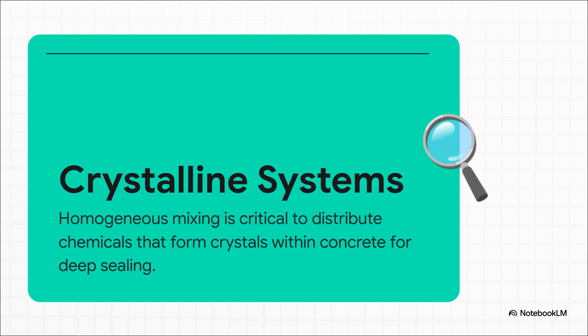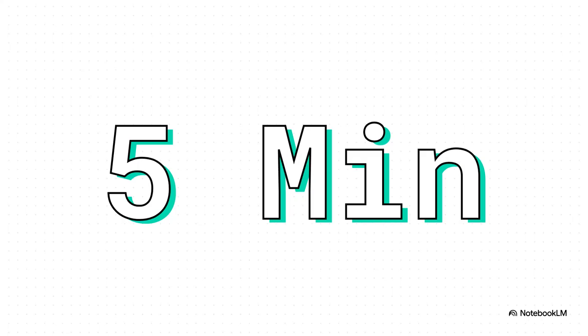They work by actually growing crystals inside the pores of the concrete to block water. For that to happen, the active chemicals have to be perfectly, evenly distributed through the whole mix. If they're not, you'll have unprotected pathways for water to sneak right through. And that's exactly why the recommended mixing time is even longer for these. We're talking a minimum of 5 minutes.